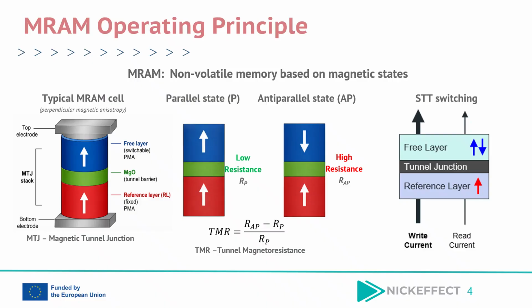The basic element of MRAM is the magnetic tunnel junction, or MTJ, shown on the left side of the slide. The MTJ consists of 2 ferromagnetic layers separated by a thin MgO tunnel barrier. The reference layer has fixed magnetization, while the free layer can switch its magnetic state.